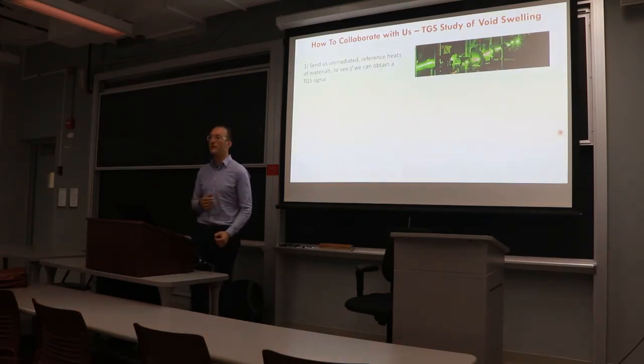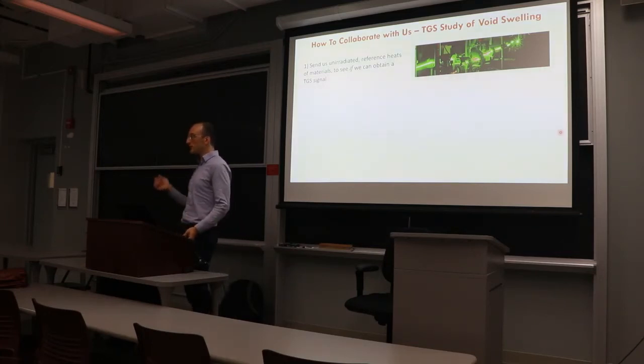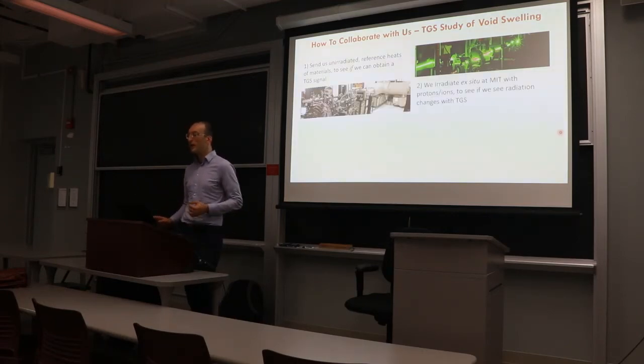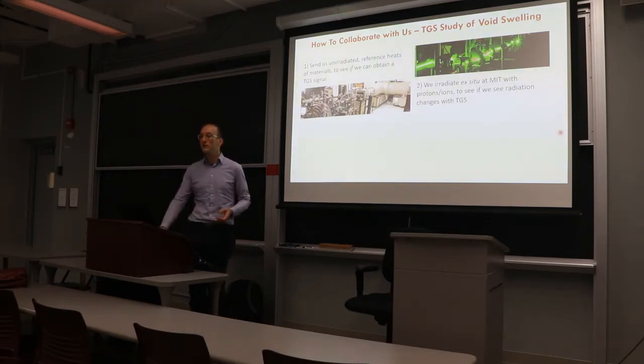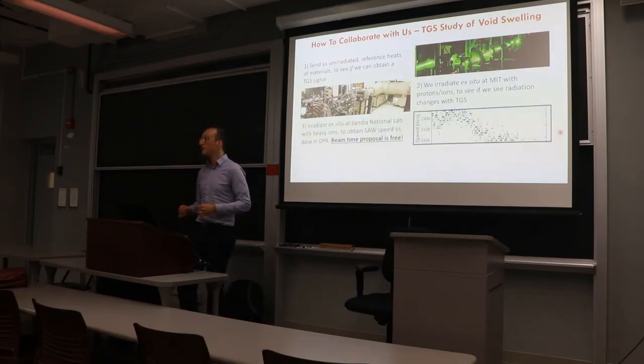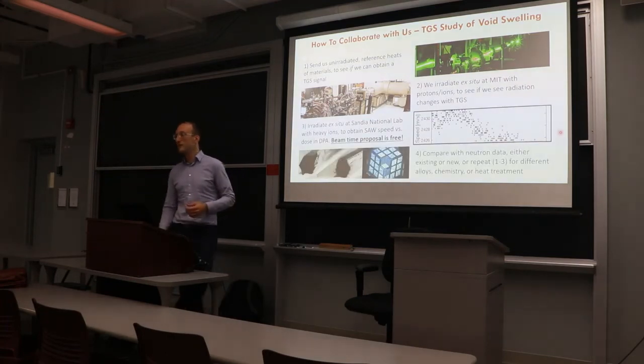Then pick your variable to vary, whether it's temperature, strain, corrosion in a transparent fluid, radiation, all of the above, and we can try an ex situ experiment, where we can either irradiate or you can send us pre-irradiated specimens and see whether or not we see a change with the variable of interest, at which point we can go in together and write one of these beam time proposals at Sandia National Lab to do an in situ experiment, where you can get a year's worth of data in an afternoon. And then sky's the limit.